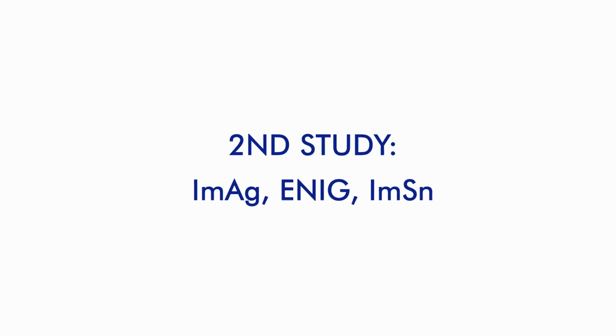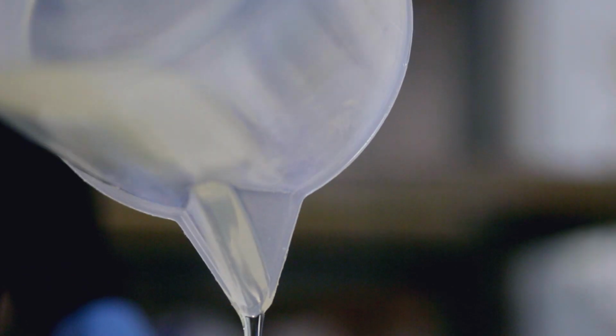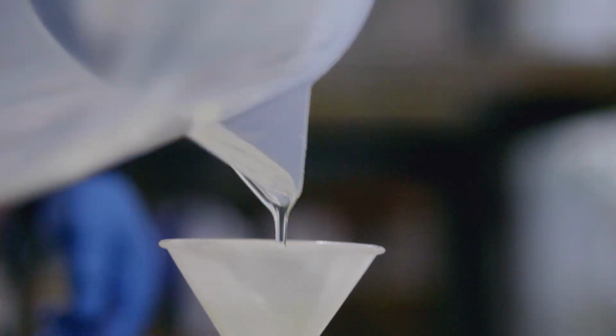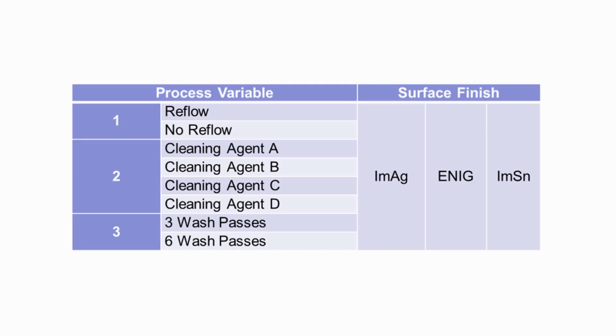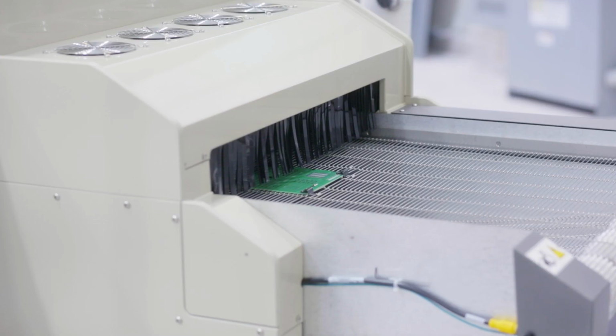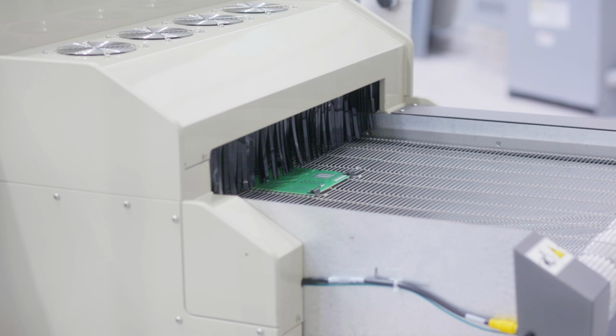In the second study, three other surface finishes were studied: immersion silver, ENIG, as well as immersion tin. Four different cleaning agents were used in the study. One was an alkaline uninhibited surfactant-based product, an alkaline inhibited surfactant-based product, an alkaline microphase product, as well as a pH-neutral microphase product. Different conditions were also tested, such as a reflow condition as well as a no reflow condition, as well as multiple passes. Three passes versus six passes were also tested to determine a worst-case scenario.